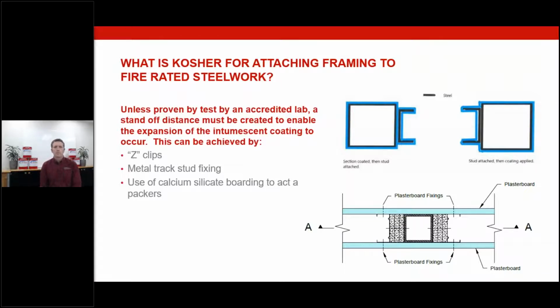You can also use calcium silicate boarding to act as packers. If you look on the bottom right hand side, there's a bit of description there of how to affix your plasterboard onto either a column or a beam. Let's just say it's a column in this particular instance. Using the calcium silicate boarding to attach onto your fire-rated column, protecting those two particular sides, then using track stud and then plasterboard fixings indirectly into that metal track stud fixing. So the plasterboard will burn away and will reveal the intumescent coating that will expand on those particular sides, and then calcium silicate boarding will protect the remaining two sides of that particular member.